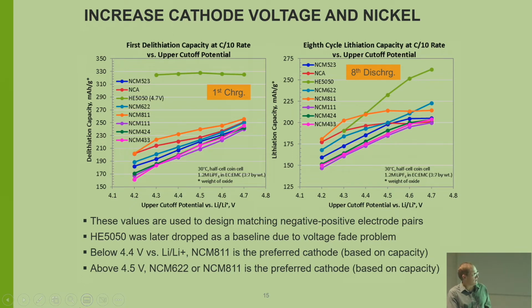So the goal is to try to stabilize these materials. One reason you're going for a higher nickel is partly to reduce the cost, because you're taking out cobalt, putting in nickel. Cobalt is expensive. But also you get an increase in capacity, therefore an increase of energy, as you increase the amount of nickel.